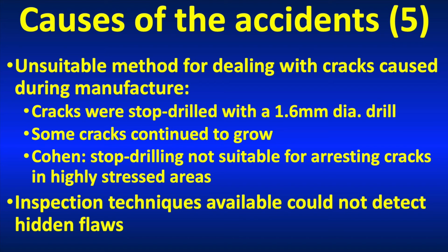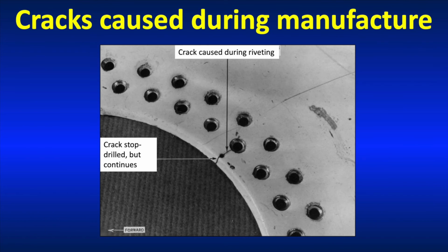So, what are they going to do to deal with these cracks? Let's have a look here. Well, there's a crack caused during the riveting process. This has obviously been de-riveted now. So they put a 1.6mm diameter drill stop hole in to stop the crack, but this particular crack kept growing, so it wasn't really a very effective technique. And in fact, Lord Cohen in his report said, what in heaven's name are you doing using stop drilling to stop cracks in a highly stressed area? It's just highly inappropriate.